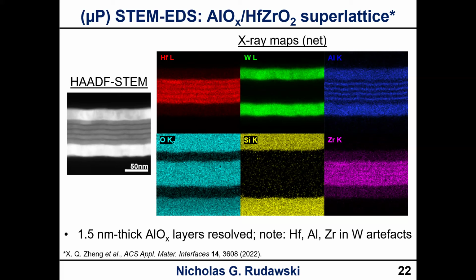Okay, I would like to point out though that we are seeing some artifacts, fortunately. We see hafnium, aluminum, and zirconium in the tungsten, which could be a discussion completely unto itself about why we see that. I did want to point that out. Again, you'll notice there's only a subscript written for the oxygen K.